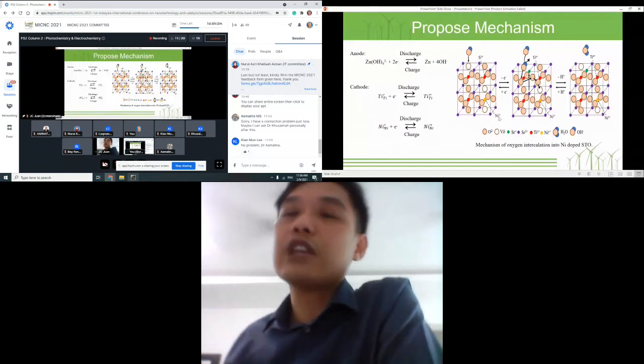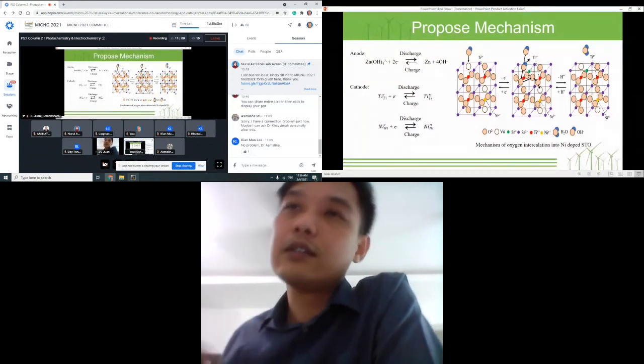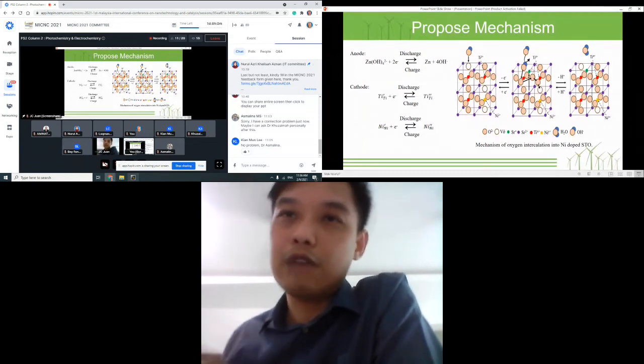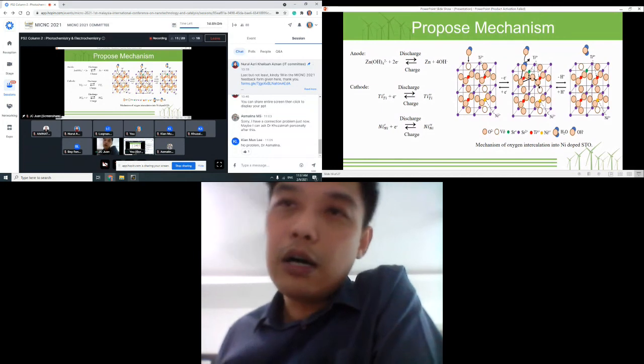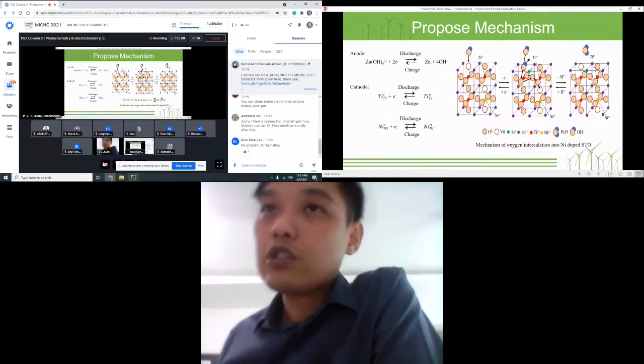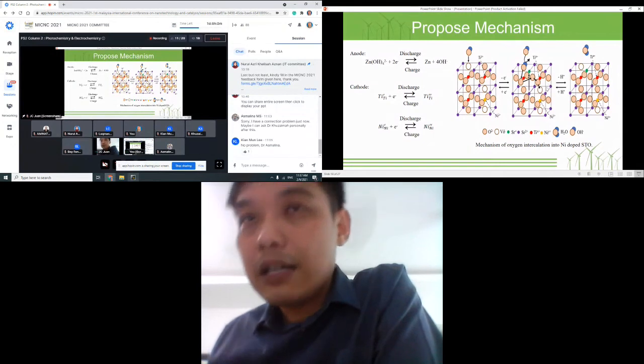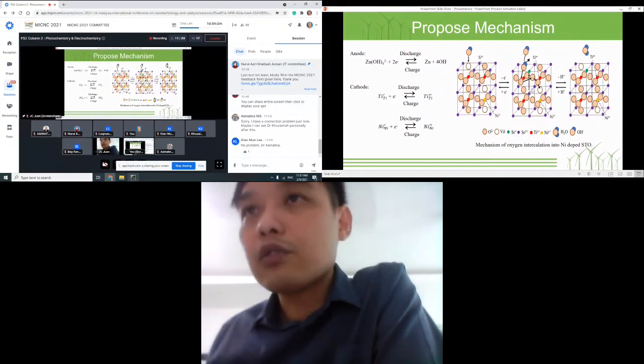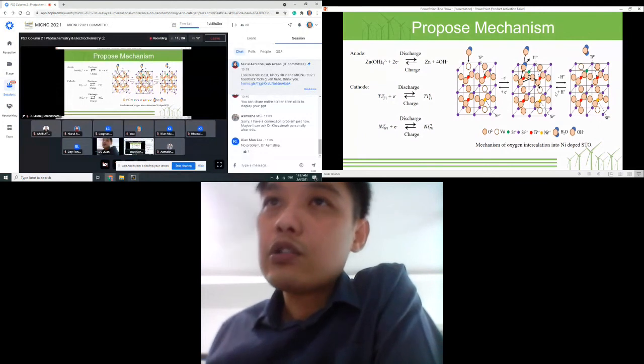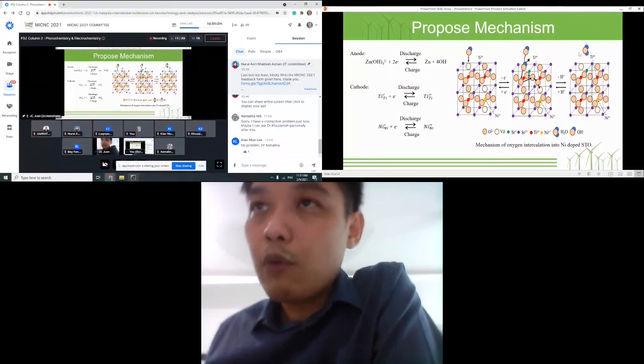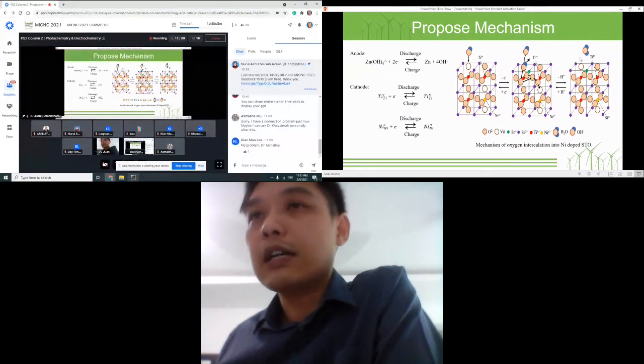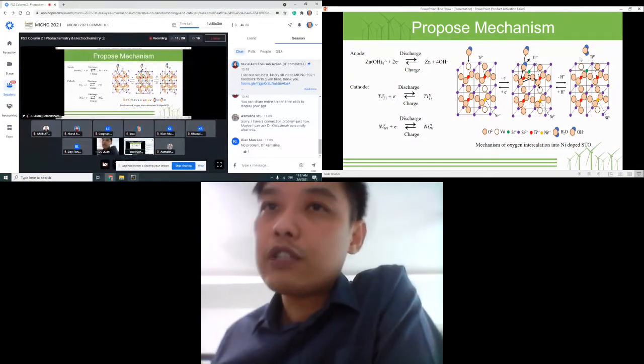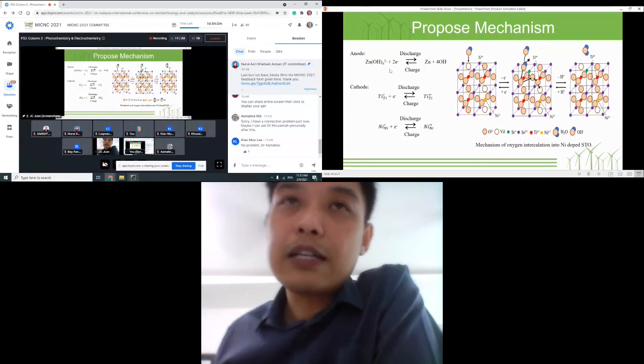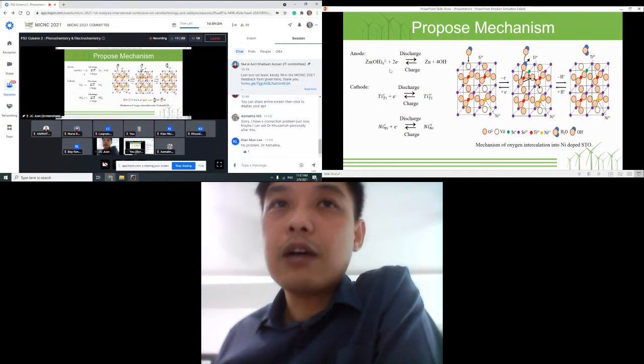So this is a charge-discharge mechanism. They increase the probability of having more electrons. As we understand, more electrons means more capacity. So this is what's happening here: charge and then discharge. To balance it out, because we have this electrolyte, it also balances out the water molecule here. So this is the advantage of having the oxygen vacancy. This is the first mechanism that we propose and have published so far for the anode and the cathodes, using this rechargeable alkaline zinc battery.